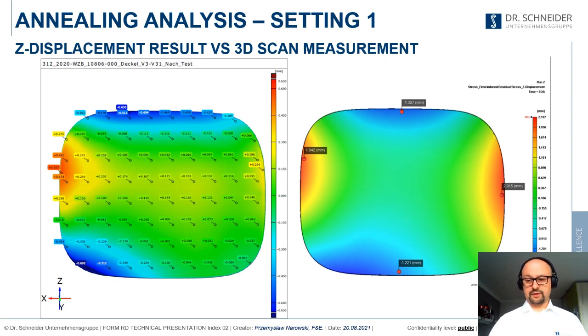So the general picture is the same. The real part goes up and goes down in the same areas as in the simulation. But the exact values are completely different. Especially here, we have a value that is more than 2 millimeters, and here it is something like 0.2. So the difference between the simulation, our prediction, and the reality is almost an order of magnitude, which is not very satisfying.